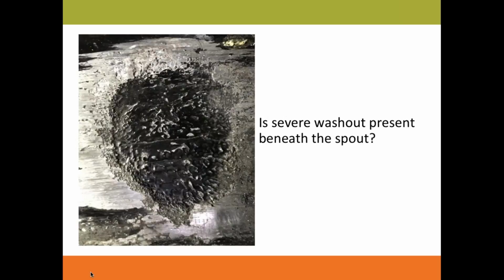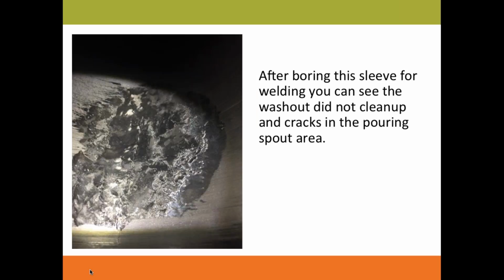If you look at this sleeve here, it has severe washout. We went ahead and cleaned under the pouring spout of this sleeve, and you'll see in the next slide it didn't clean up in the prep, and also it revealed a crack. Again, this is not a good candidate to bore weld because the crack will propagate.